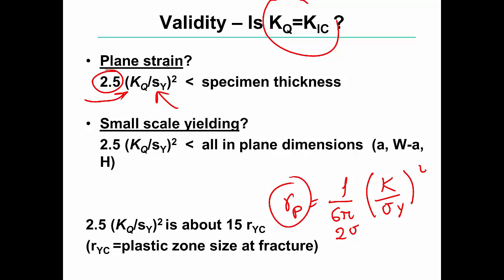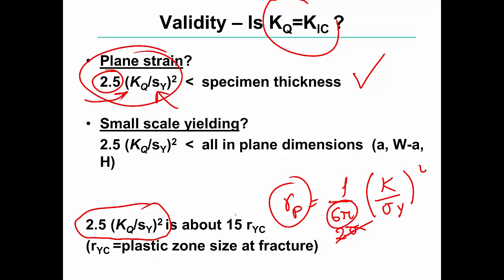So this expression here actually has length dimensions, and if this is smaller than the specimen's thickness, then the plane strain conditions are satisfied. This expression for plane strain is about 15 times the plastic zone, the maximum plastic zone, the plastic zone at failure. So if the thickness is much larger than this value, then ASTM standards say that the plane strain conditions are satisfied.